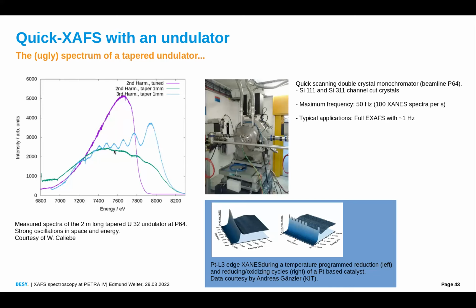Wolfgang showed that the spectrum looks much better, much smoother, if you don't use the odd harmonics, but the even harmonics. This is shown here for the second harmonic. But still, it's not ideal, and it's not infinitely white, certainly not. But it's possible to use it, as was shown at P64. One can do XAFS experiments with such an undulator. It can be done, but it's not ideal.